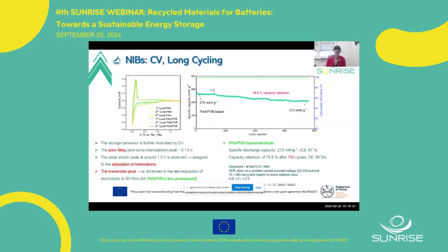Regarding the initial irreversible process, the PAA-PVB showed the less irreversible peak, which is in good agreement with the better initial Coulombic efficiency of this electrode. We also evaluated the cycling performance over around 800 cycles, and this electrode showed capacity retention of around 79% with a very high initial Coulombic efficiency of 87%, and upon cycling, the Coulombic efficiency reached 99.9%. That is a very good result.